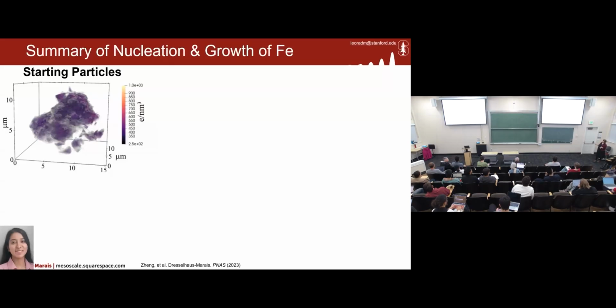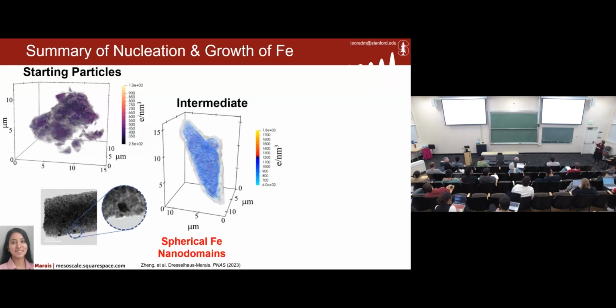So now let's actually look at some pictures, and what we see is that we start off with these beautiful particles that show us effectively nothing at all, because we can't really see the particles. They're just too small for us to be able to resolve at this point. But as we start to now zoom over in time, we now, after 2 hours, see this thresholded view where everything blue is now an oxide and everything orange is a metal. So you can see now these new spherical particles that are starting to form internally inside of the iron that correspond to actual iron formation, i.e. this is the nucleation and growth of that phase we're all hunting for in this iron-making process.